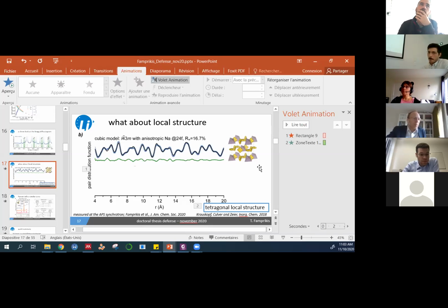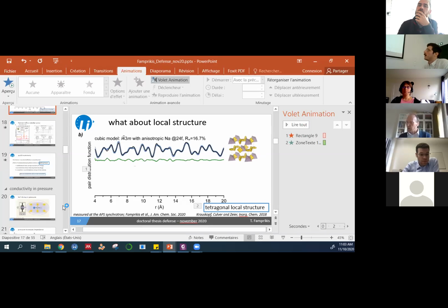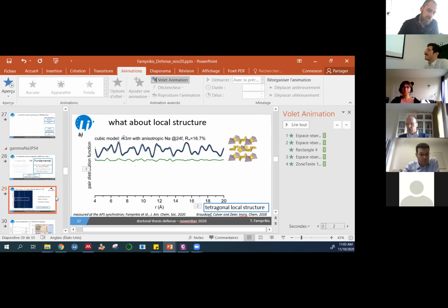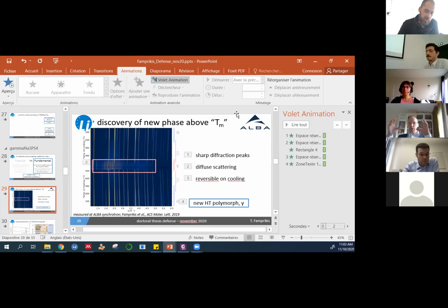Of course, it keeps being intriguing. Your phase transition towards the gamma phase, where you ended up with this local order. I thought it was a very nice description of this mesophasic material, where you show there's actually no correlation between how one sodium or PS4 group sees the next one, that they hardly see each other anymore, right? Yeah. That's super intriguing. And wouldn't phonons also be a way to study this? Because phonons are the collaborative motion of these units. So it actually requires that they see each other. So it must have a drastic impact on it.